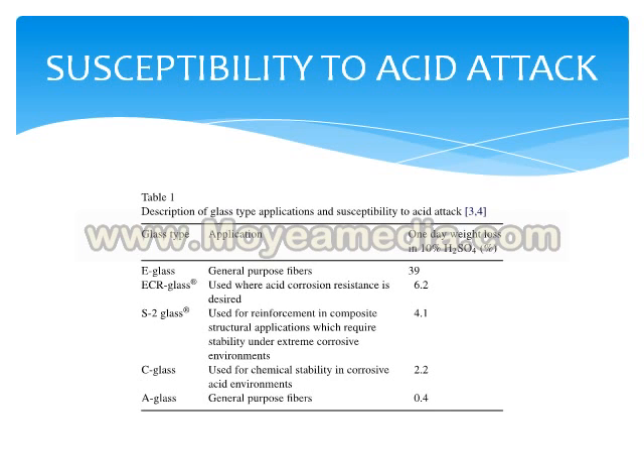This table shows the weight loss of commonly used fiberglass components in an acid solution, which is not a direct measurement of stress corrosion cracking performance, but it has been shown to correlate with the performance of fiberglass structures made with these types of E-glass in corrosive environments. As you can see, E-glass, the most inexpensive type of fiberglass, shows the greatest susceptibility to acid attack, and then there are specialized glasses such as A and C glass, which show performance an order of magnitude better. So typically you'll have an outer layer of C glass around the part being primarily composed of E glass.